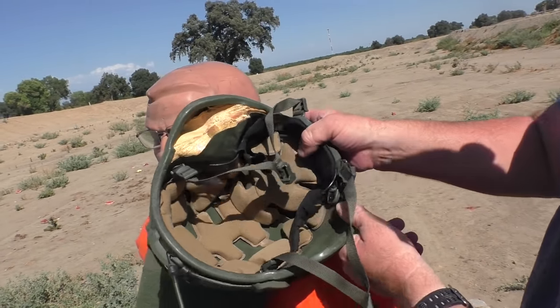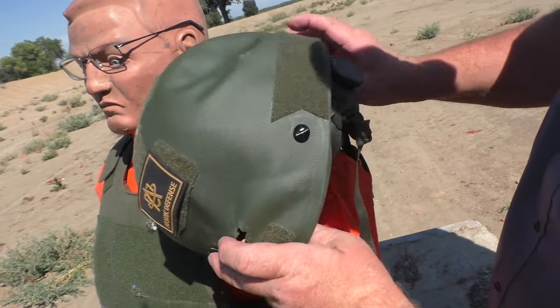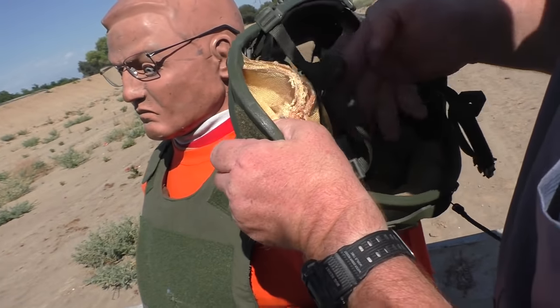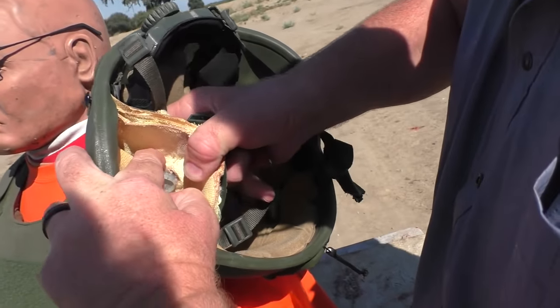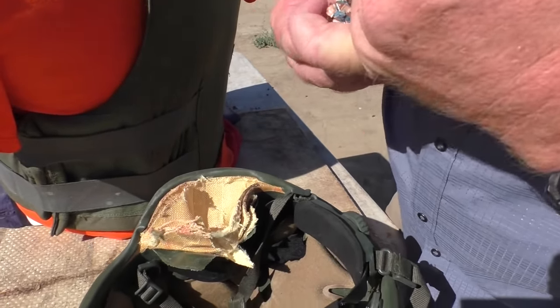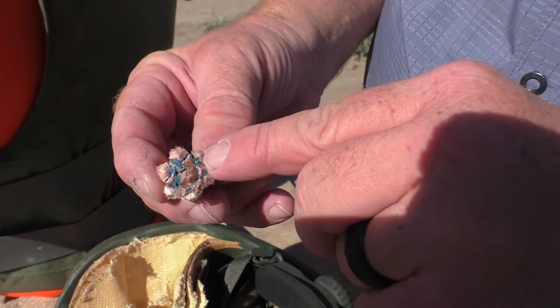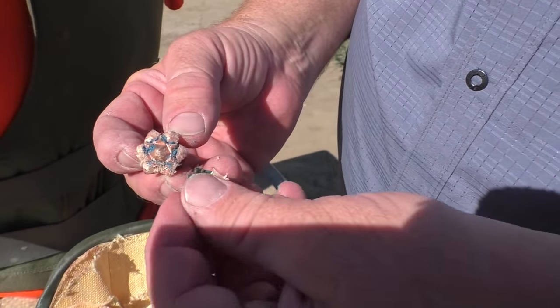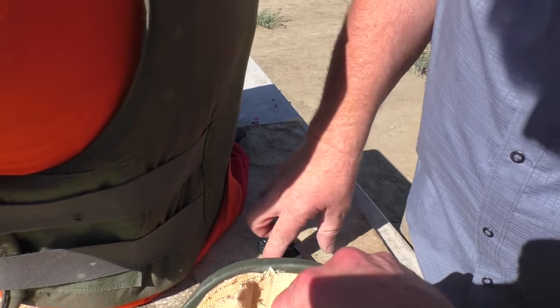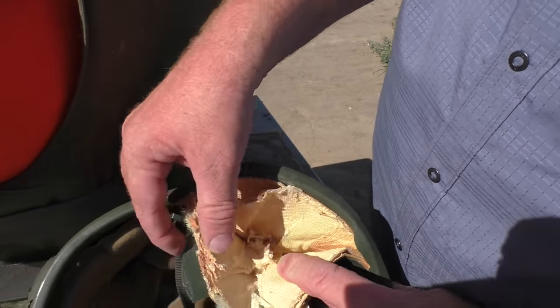That was some pretty impressive damage — I think that was the two-ounce slug. Look at the pattern it tattooed into the side. It carved a big hole and filleted all of the laminated Kevlar pieces. There's the base of it inside. After about 15 minutes of digging with pliers, we finally got it out. It flared out, which caused it to anchor itself into the Kevlar like fish hooks or a molly anchor. We found burnt tape down in the crevasses and a layer of melted plastic — it just caught everything and took it with it. It almost made it through — just two layers stopped it. We had to saw down to relieve pressure then pulled it out backwards.